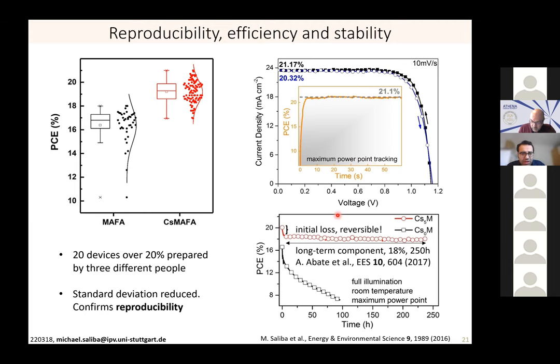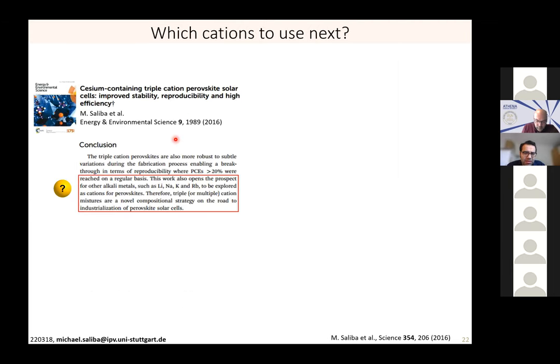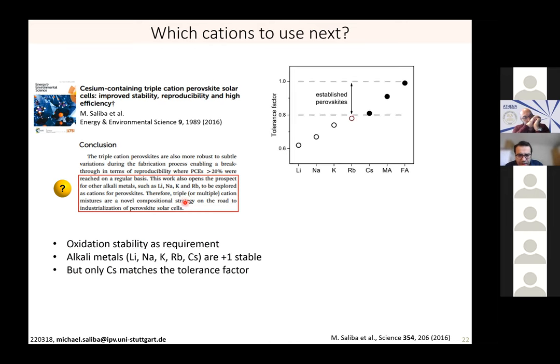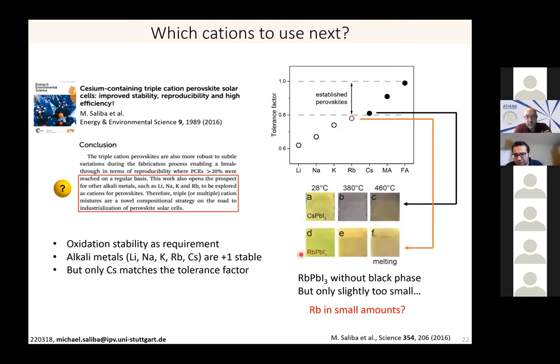So then, and it's written in the last sentence of the conclusion of this paper, this also opens the prospect for all the other alkali metals, including, for example, potassium, but also rubidium. And that's something that a lot of people started looking at. Maybe there is space for a triple or multiple cation approach. And why the alkali metals? Because they are plus one stable, almost by definition, by being in the first group. But the issue is only cesium fits into this equation. And you saw previously the alkali metals are usually too small. And you see here as well, they are so small, they never form a black phase. They're simply outside of the correct range; even at very high temperatures, they don't go black.